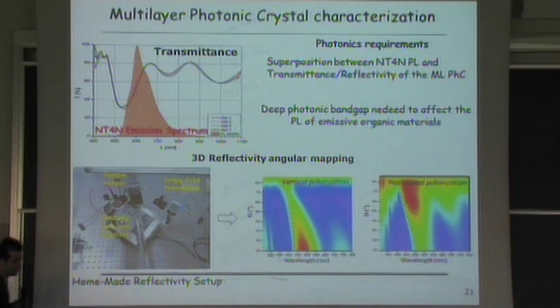Also, the photonic requirements are stringent because we need the superimposition between the NT4N photoluminescence and the transmittance of the photonic crystal. Moreover, we need a deep photonic band gap to affect the photoluminescence of the emissive organic material. We used our homemade reflectivity setup to take out these two 3D reflectivity angular maps.